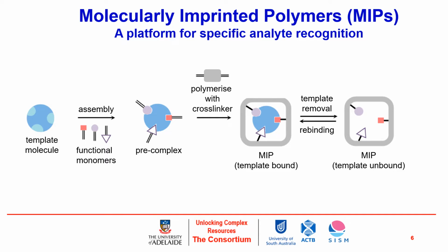Initially, when I started this project, the idea of molecular complementarity lended itself to the development of molecularly imprinted polymers. Now, the principle behind molecularly imprinted polymers involves the isolation of a template molecule, taking that template molecule and its unique chemical characteristics and picking complementary functional monomers that are able to interact with the key sites of that template molecule, and then cross-linking them with a polymer backbone, which forms a degree of pockets and pores that are able to bind with that identifiable template molecule, which can then be removed through dissolution into a solvent and then used as a platform for sensing because of this desorption, adsorption, equilibrium property, where the template molecule, which might be your analyte of interest, is able to bind and unbind in a concentration dependent manner.